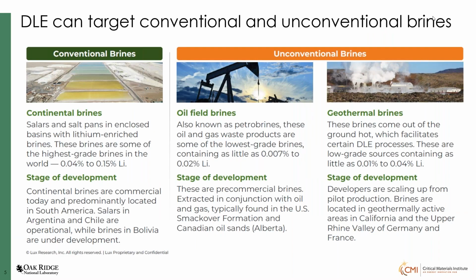So direct lithium extraction, we are targeting brines, the conventional and unconventional brines. The conventional brines, you can see on the first one, are continental brines. These are salars and salt pans in enclosed basins, lithium-enriched basins. Here the concentrations are high, and can vary from 0.04% to 0.15% of lithium. That's quite high. Continental brines are commercial today, predominantly in South America, with salars in Argentina and Chile in operation, and Bolivia under development. But this is solar evaporation, and the method can take 12 to 18 months. You will see the slide on the next one.